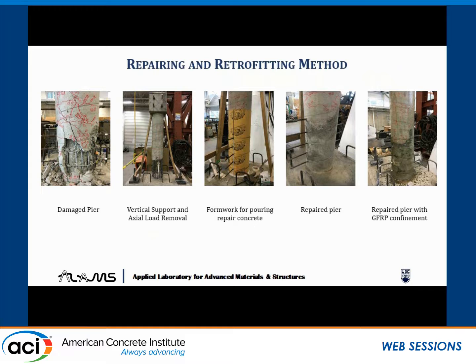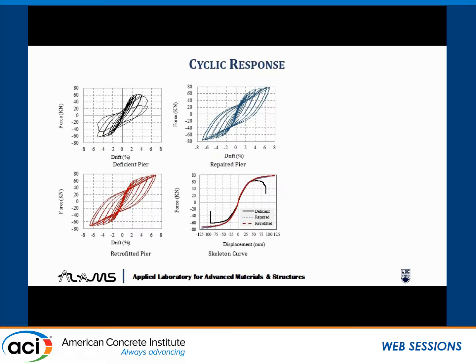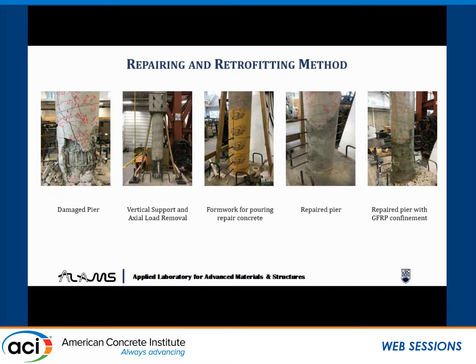So after the testing of the original control specimen, you had significant spalling of concrete, and you had bar buckling. Before we started repairing it, we removed the damaged concrete. We had to provide support so that the column doesn't fall. Then we did the concrete grouting, so we repaired it, and then we started. Okay, after this one, we repaired with GFRP confinement.